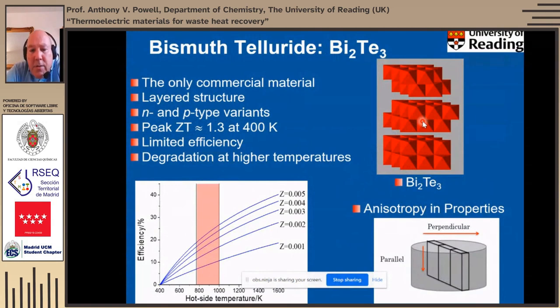That in itself can introduce some problems because it means that the properties are generally very anisotropic. And often in terms of powder consolidation, where we're pressing an ingot, we need to be able to cut that ingot in particular ways in order to measure the transport properties, both parallel and perpendicular to the pressing direction, because the anisotropic structure gives us an anisotropy in terms of properties. The nice thing about bismuth telluride is that it's possible to make chemically compatible N and P type variants. So if you remember, the thermoelectric device has both N and P type semiconductors. So we could make both N and P type versions of it through suitable doping.